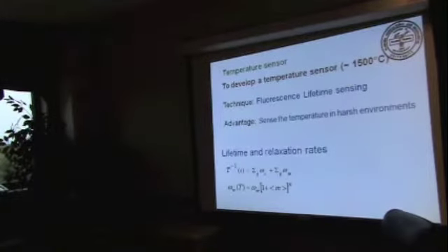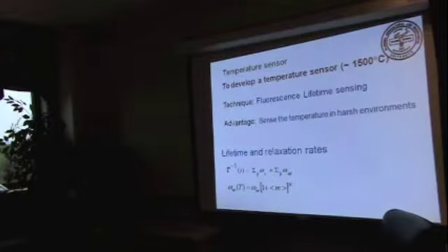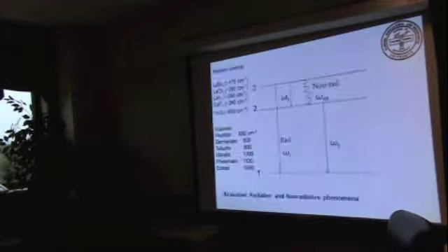Whenever you measure the lifetime, this inverse of lifetime is related to the sum of these two relaxation rates. The radiative relaxation rate doesn't depend on the temperature. It's independent of temperature, whereas the non-radiative relaxation depends on the temperature. If you heat the material, this factor increases. When this factor increases, the lifetime decreases. Okay? So that is the concept of lifetime temperature sensing. That's what we are going to use.